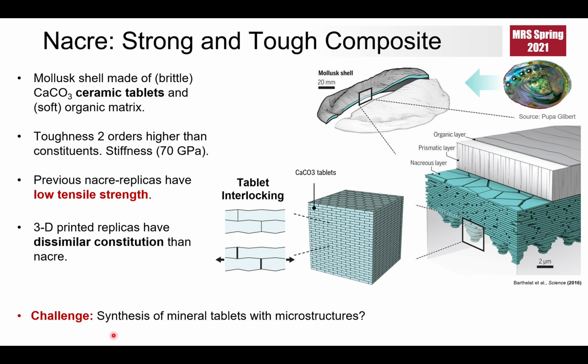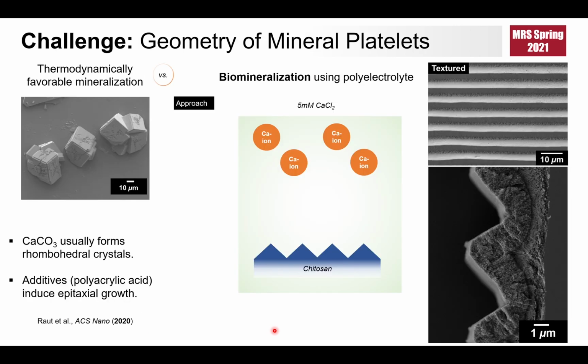For the fabrication of the composite, the key challenge is to replicate the wavy platelets by crystallization of calcium carbonate. Usually, calcium carbonate crystallizes into rhombohedral crystals. On the other hand, in nacre, the wavy platelets are formed by a process called biomineralization that enables control over the geometry of mineral crystals.